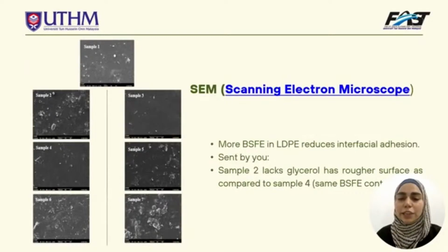The next one is scanning electron microscope results. If we see the analysis of the micrographs obtained after SEM, this graph shows that as the BSFE content is increasing, the interfacial adhesion between the components is decreasing. If you see sample 2 and 4, both have the same black soldier fly exuviae concentration of 10%. But sample 2 is without glycerol while sample 4 is with glycerol. So sample 4 has a smoother surface as compared to sample 2. Sample 2 has a rough surface because it lacks the plasticizer, glycerol.